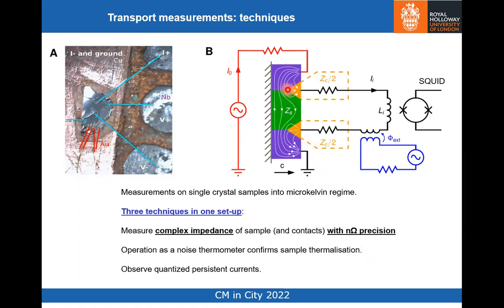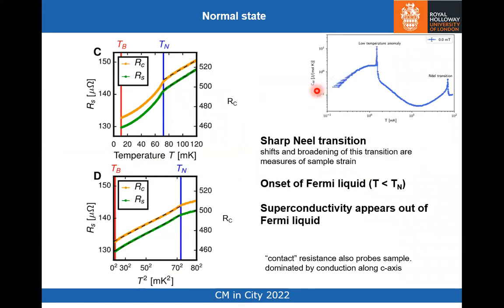We can operate that in the normal state. We can operate this device as a noise thermometer. So this is resistive. There's Johnson-Nyquist noise. It's driving current through this input circuit of the SQUID. The SQUID is a current-voltage amplifier. So using this as a noise thermometer then confirms the sample thermalization, and in early work actually confirmed that the loss of resistance, so the disappearance of Johnson-Nyquist noise, is associated with the turning off of the resistance at the superconducting transition. And if the sample is superconducting, then we can have a closed superconducting loop in which you would expect to see persistent currents. So we can see all of these things.